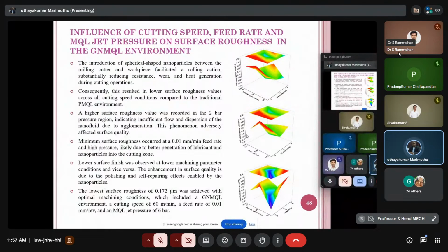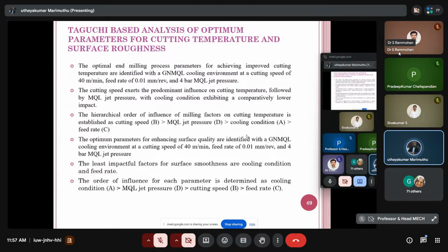Minimum surface roughness occurred at a feed rate of 0.01 mm per minute at high pressure, likely due to better penetration of lubricant and nanoparticles into the cutting zone. Lower surface roughness was observed at lower machining parameter conditions and vice versa. The enhancement in surface quality is due to the polishing and surface repairing effect enabled by the nanoparticles. The lowest surface roughness of 0.172 micron was achieved with optimal machining conditions, which included a GNMQL environment, a cutting speed of 60 meters per minute, and a feed rate of 0.01, and so on. This is about the Taguchi-based analysis of optimum parameters for cutting temperature and surface roughness.